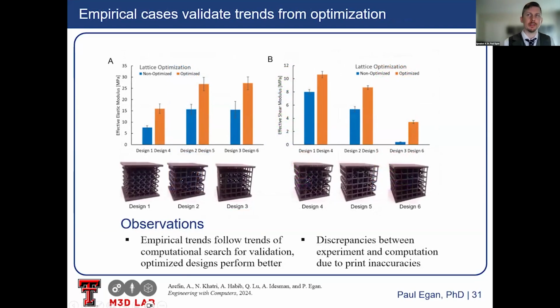And so whenever we compared this to the physical case, mostly for convenience and efficiency, we used the nylon powder printer, but you could also use the biocompatible materials and the SLA resins as well. So if you look at these optimized versus the non-optimized designs, across the board, the best ones in tension and the best ones in shear, the optimized versions do better than the non-optimized ones. And even here in the middle, where you're compromising the values, the one that has a combination of shear and elastic modulus does both of those better than the non-optimized version.